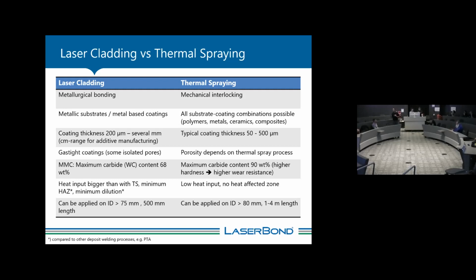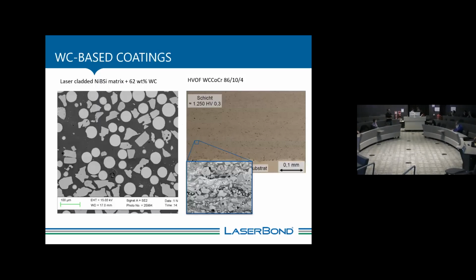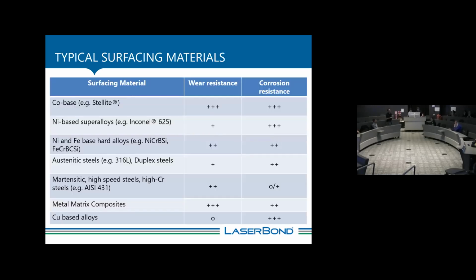Laser cladding has some dilution, it's smaller than in a welding process, but it's still there. On the other hand, the thermal spraying, same magnification, both metal matrix composite coatings, laser cladding with big carbides, about 25 microns plus. So, just very quickly, the materials we work on a daily basis with give us the big leeway we have when it comes to tailoring coating solutions.